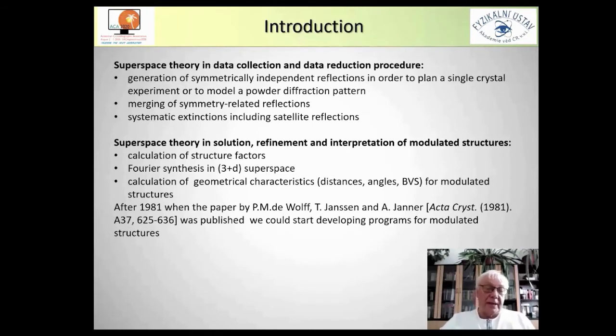The superspace theory can be used also in solution and refinement and interpretation of modulated structures. First, it can be used to simplify calculation of structure factors by using symmetry. It can be used to produce Fourier transform, Fourier synthesis in 3+d dimensional space, and calculation of geometric characteristics, something like distances, angles, bond valence sum for modulated structures. After the paper of De Wolf, Janssen, Janner was published in 1981, we could start developing programs for modulated structures.